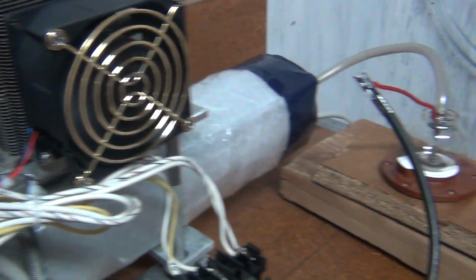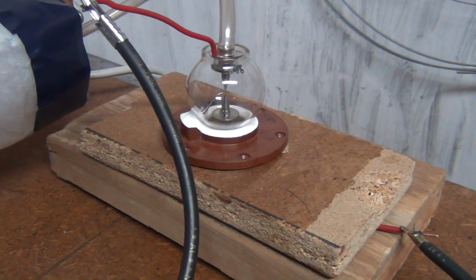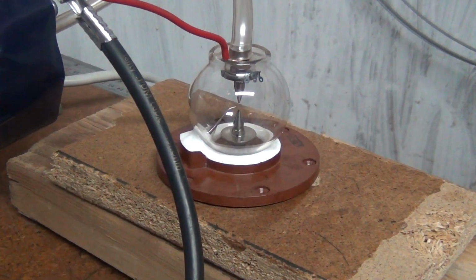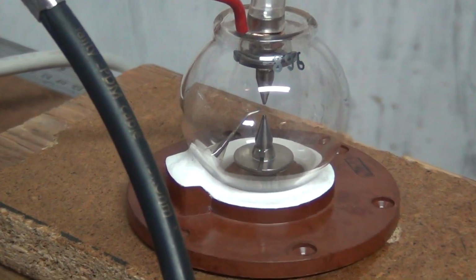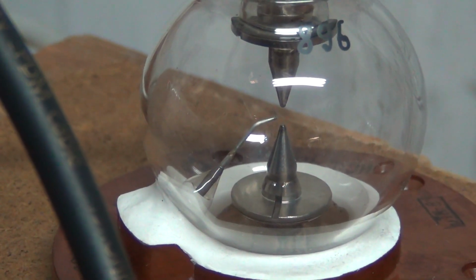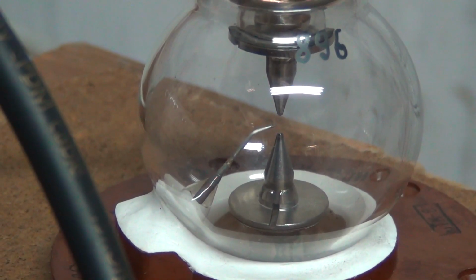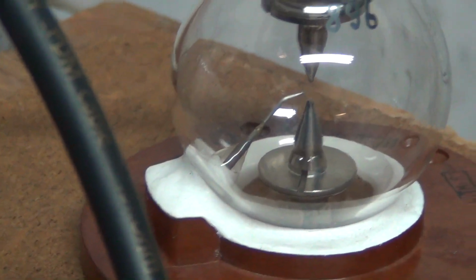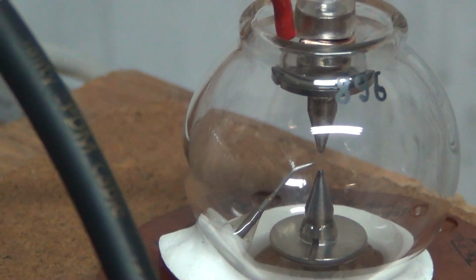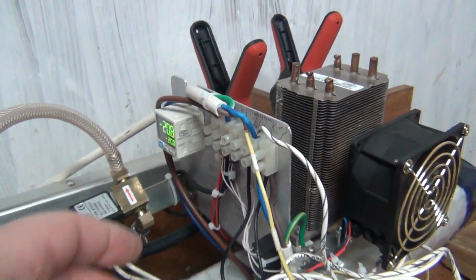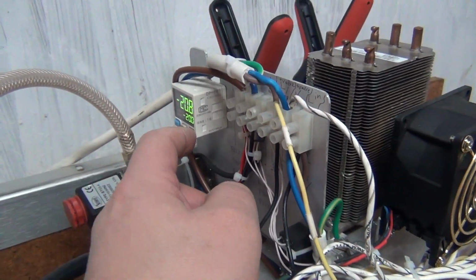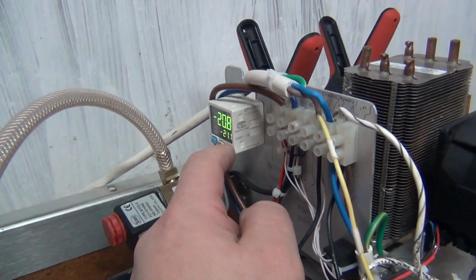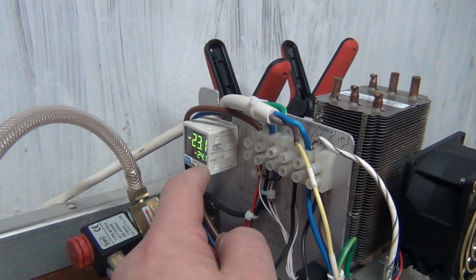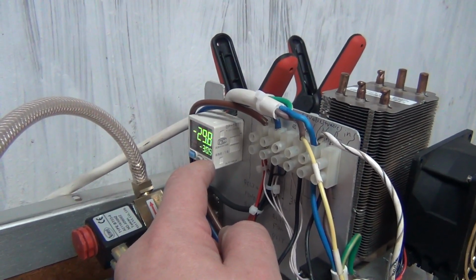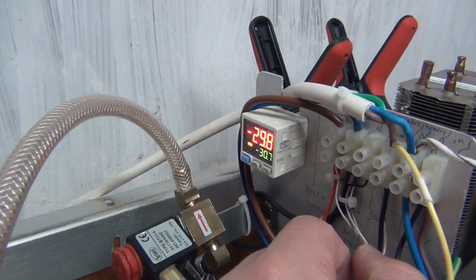Now I started to decrease pressure step by step. I started from minus 20 kilopascals, and as you can see there is a breakdown, this sparkle between the dots only. After I will check, of course, for interference, and at least in this part my theory is correct. When this sparkle starts to fill this cone, in this case interference becomes much more severe.